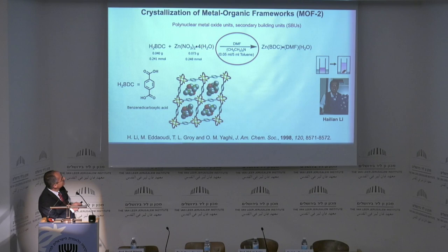It turns out that this cocktail of solvent and base, the base deprotonates the acid. If you dilute this base with solvent, you can control the nucleation, and in the end, instead of getting an amorphous material, you get a crystalline material.